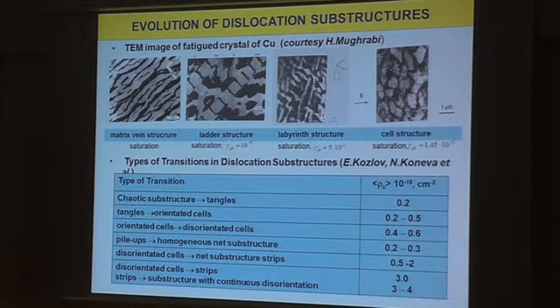For introductory reasons, I would like to attract your attention to a characteristic pattern during fatigue related to multi-scale persistent band evolution, when we have transformation of dislocation substructures with a pronounced mechanism of saturation also, because we have change of dislocation density and spacing between characteristic structures. Similar results were obtained also in Russia, where very pronounced bifurcations were found in terms of characteristic dislocation density that exactly correspond to this pattern.